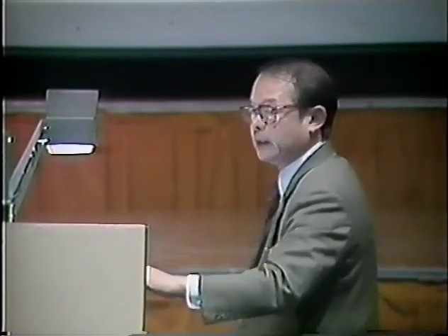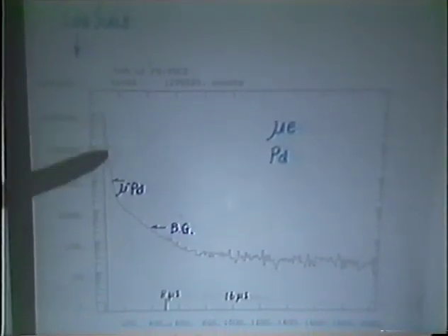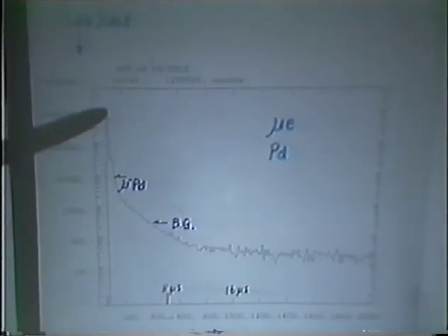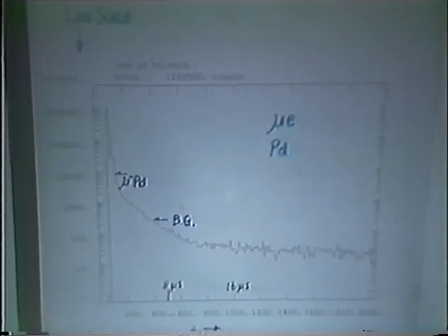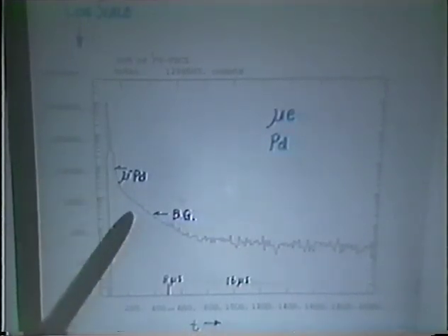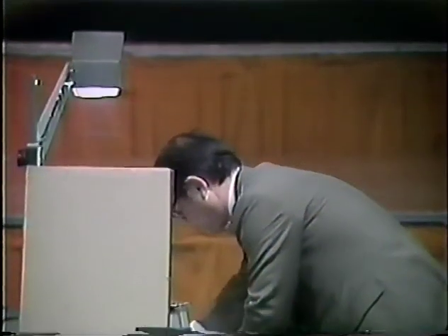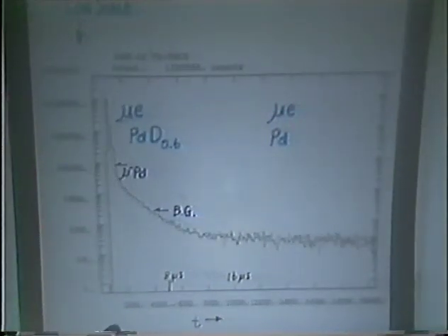Now let me show you the result. This is the result of the mu decay presented in logarithmic scale for the pure palladium. This is time. This short time component belongs to the mu minus stopped in the palladium. This is a background. And when we change to the palladium deuterium placed in open air, the data is just the same. So mainly the muon is captured to the palladium.